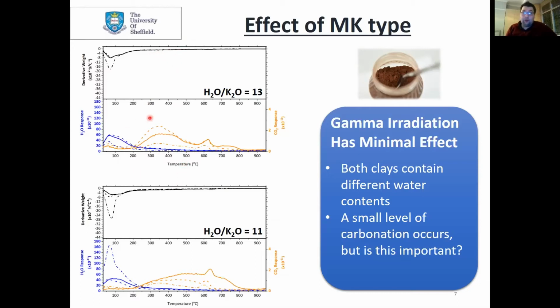You can also see there's a slight bump in the curve here, related to carbonation of the sample—irradiation induces carbonation. Carbonation is a worry to the nuclear industry as it can cause expansion and cracking and things along those lines. But the level of carbonation we see here is about 0.5 weight percent of the sample, so that's not really too much to worry about.